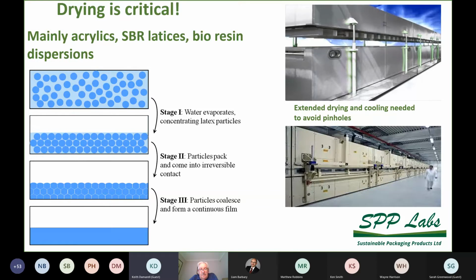So then after you've driven off the water, you then need to generate heat to coalesce and film form the coating. And then in fact, you need to apply cooling to cool down the coating to give you a final uniform resistant layer. And the cooling is important to prevent blocking. If you have a coating that's hot when you reel it up, it will stick and it will cause blocking in the roll. So drying is one of the key reasons why there are limitations for on-paper machine barrier coating solutions, but also why, to a certain extent, off-machine coating investments can be fairly high, because you need to have the extended drying capability and cooling capability to make the barrier coating work well.